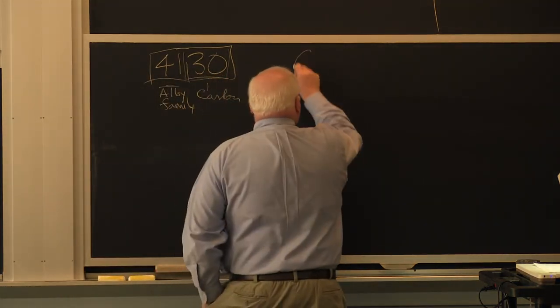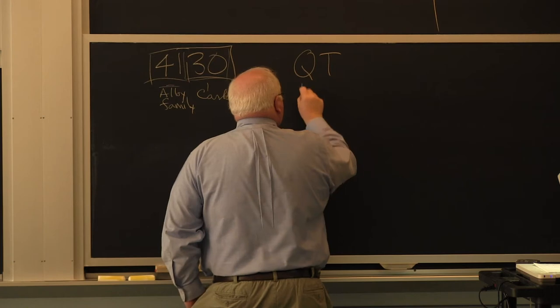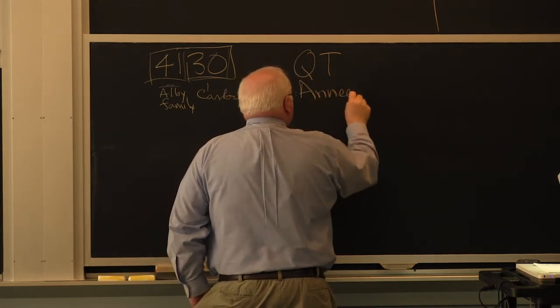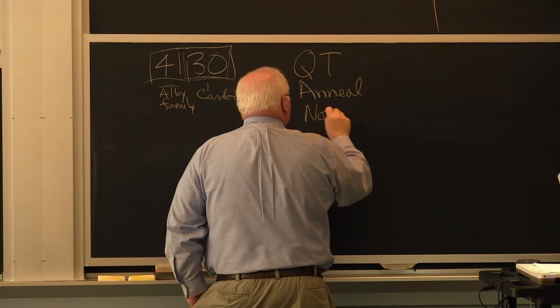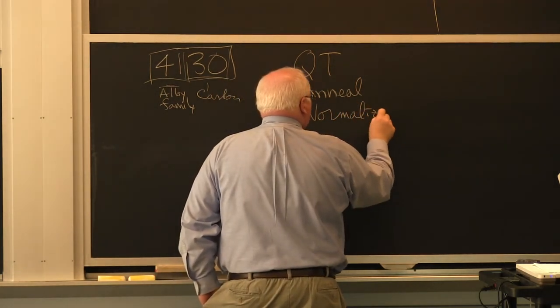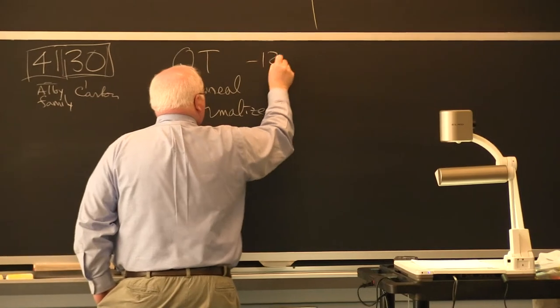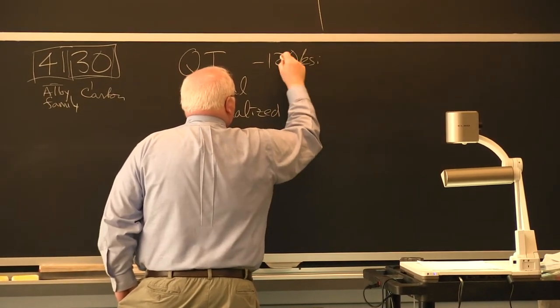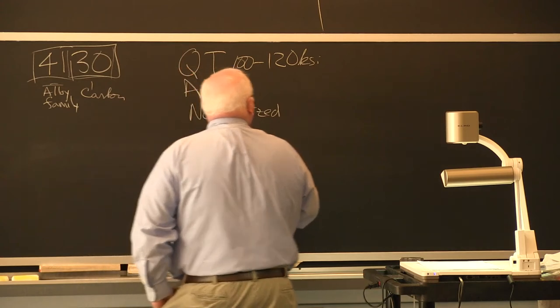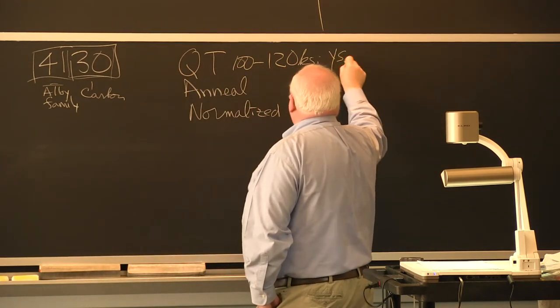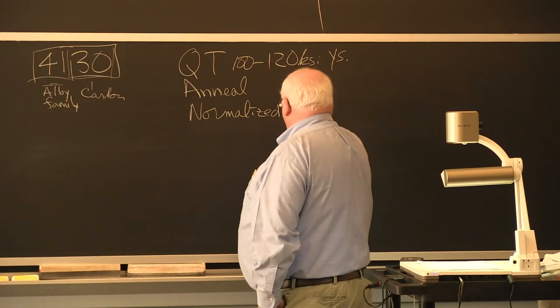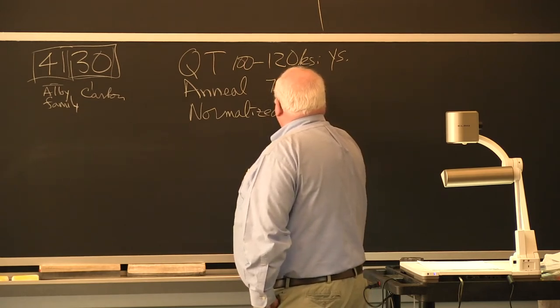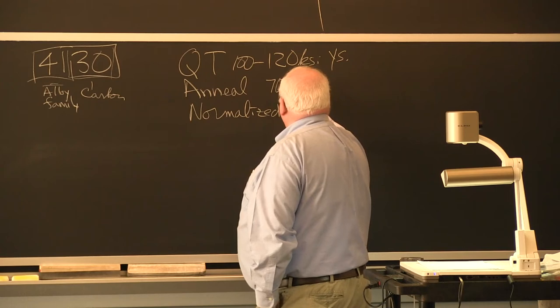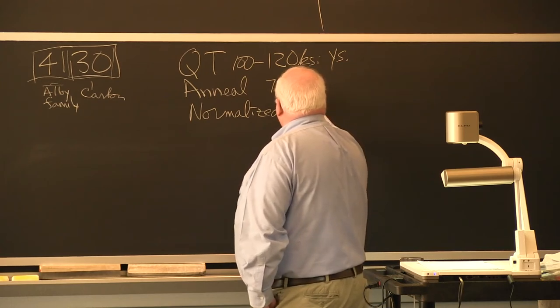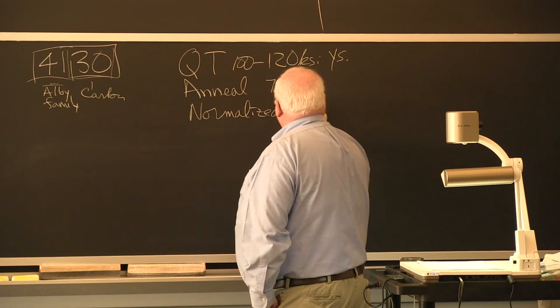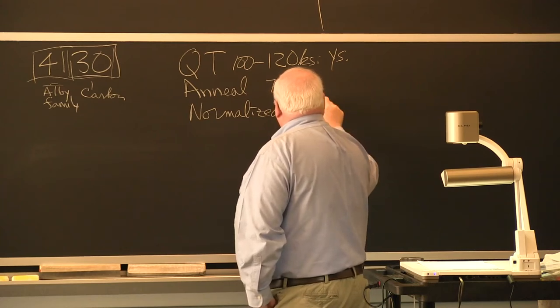Comes in three forms. If you look at the spec, quenched and tempered, annealed, and normalized. Quenched and tempered, it might have a strength of 120 KSI yield. I'll say 100 to 120, I didn't look it up. Yield strength, not much higher tensile strength. Annealed, it might be 70 to, I'll just say it's 70 KSI. And normalized, it'll probably be 90 to 100.